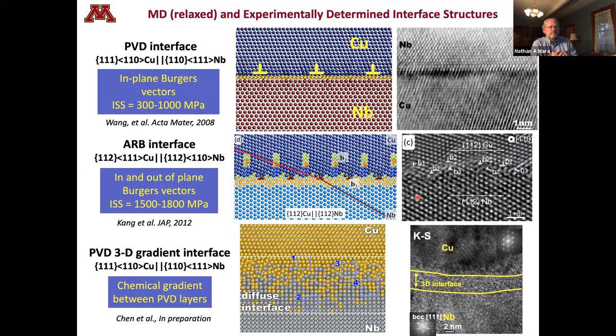And so if you change that crystallographic orientation and you change the depths or widths of those dislocations, do you change their resistance to shear also? Absolutely, yep, that's exactly right. And that's what we're playing with actually in this next 3D gradient interface.